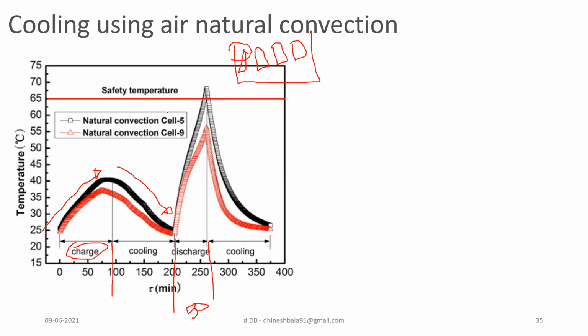Here you can see the temperature for cell number 5 and cell number 9 especially. For these two cells they have kept a thermocouple, and connected it to a system where the temperature is monitored every minute. This has been plotted with respect to the time scale. At the time of charging there is a temperature range, and the charging temperature is not enormously higher, because we are very much aware that the operating temperature limit for a lithium ion battery is 15 to 35 degrees Celsius. At the time of charging, it exceeds only to a minimal level.